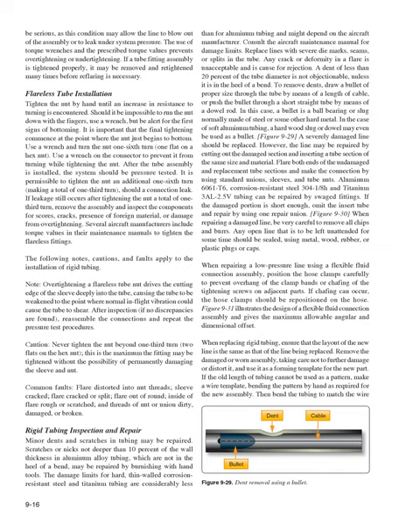If leakage still occurs after tightening the nut a total of one-third turn, remove the assembly and inspect the components for scores, cracks, presence of foreign material, or damage from over-tightening. Several aircraft manufacturers include torque values in their maintenance manuals to tighten flareless fittings. Note: over-tightening a flareless tube nut drives the cutting edge of the sleeve deeply into the tube, causing the tube to be weakened to the point where normal in-flight vibration could cause the tube to shear. Caution: never tighten the nut beyond one-third turn (two flats on the hex nut). This is the maximum the fitting may be tightened without the possibility of permanently damaging the sleeve and nut. Common faults include: flare distorted into nut threads, sleeve cracked, flare cracked or split, flare out of round, inside of flare rough or scratched, and threads of nut dirty, damaged, or broken.